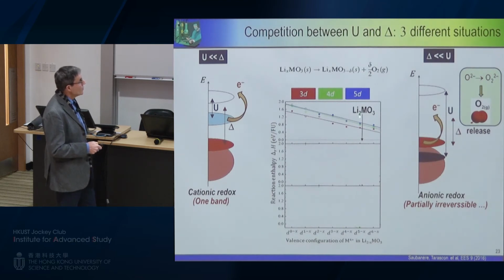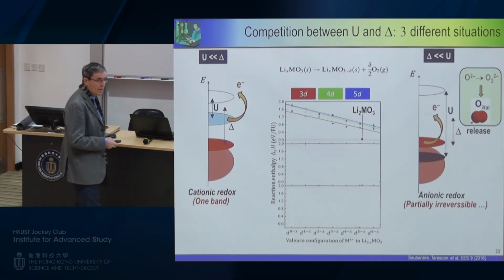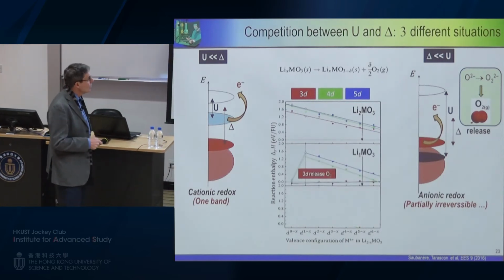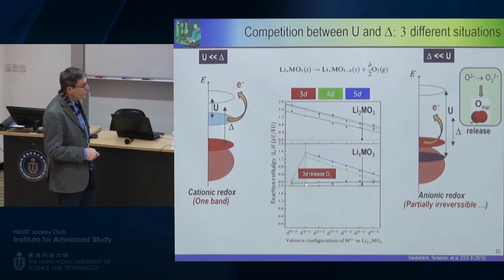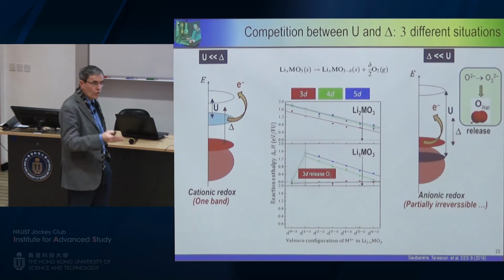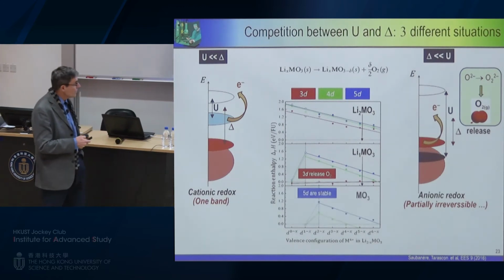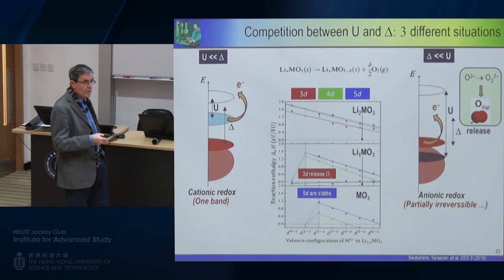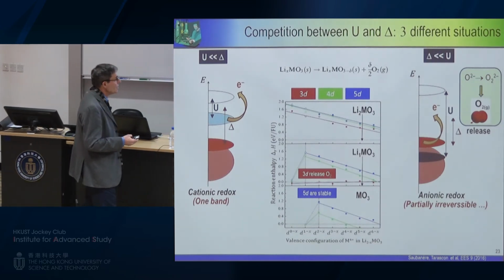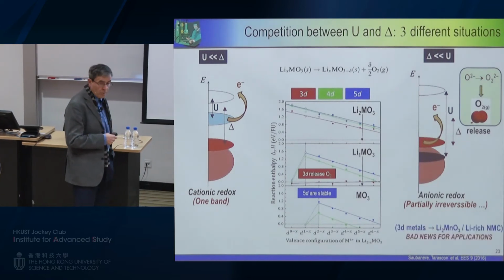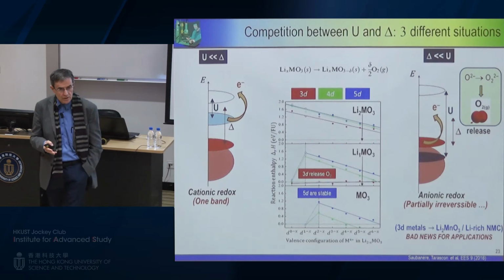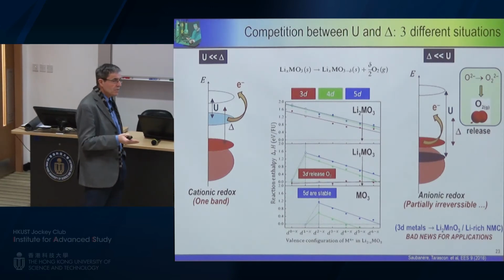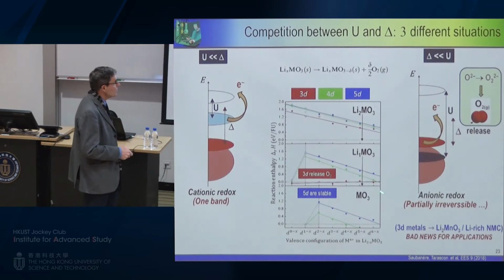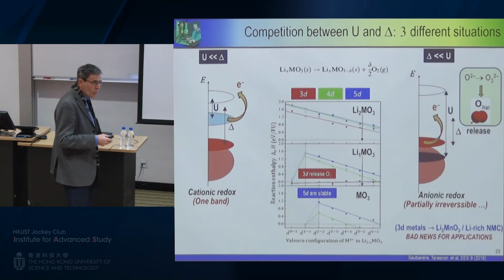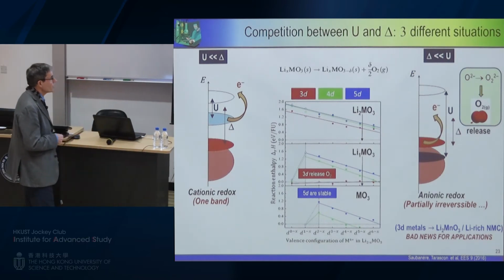And as you can see, when I take Li2MO3, in this case, all these materials are stable. Now, if I start to remove lithium, you are going to see what happens. Look, as soon as I start to remove lithium, look at the 3d metals. Here, we already start to have the release of oxygen. If I want to remove more lithium, it's even worse. And only the 4d or 5d metals are able to sustain the stability. So I will say this is only the bad news with respect to application, and why we have so much trouble really stabilizing these lithium-rich NMC, which are nearly based on 3d metals. So you can see here, there is always a small amount of oxygen release during the first reaction process.